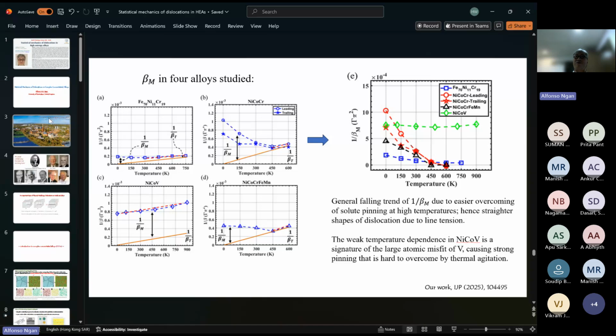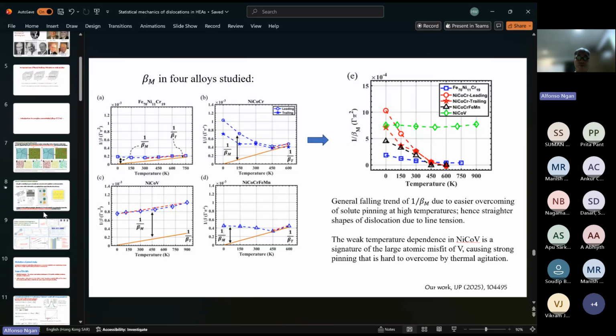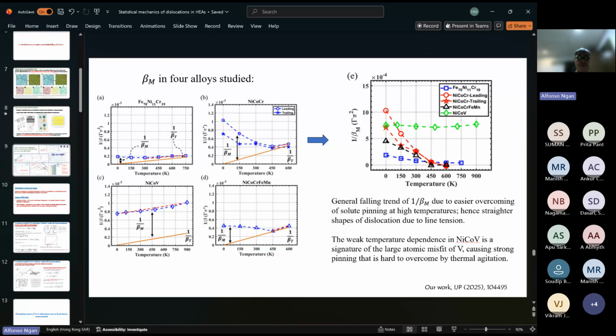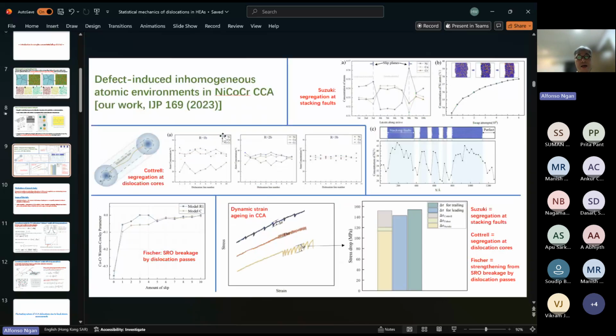It's hard to address your question quantitatively, and that conclusion that Suzuki was more prominent was only for one alloy system. For example, I spoke to Prita the other day, and she worked on a copper aluminum system. That was the reverse. I think she observed the other way around, which is Cottrell being more important than Suzuki. So I don't think that is a general trend. It very likely is material specific. It's just that in this nickel cobalt chrome, Suzuki is the major, as you can see from this yellow component, while this component is the Cottrell. But I don't think that is a general trend.